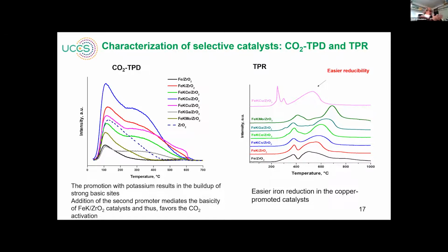For example, some elements increase the basicity, while second promoters can slightly reduce it. However, in all cases, we have very pronounced basicity of the catalyst. And also TPR. What we found in TPR is that for most catalysts, second promotion actually results in slightly poorer reducibility, with the exception of copper. For copper, we have a significant improvement of iron reducibility in the presence of copper.